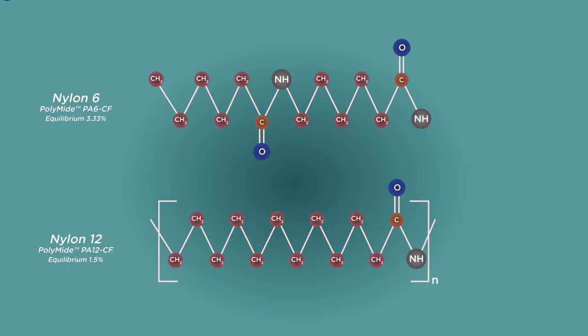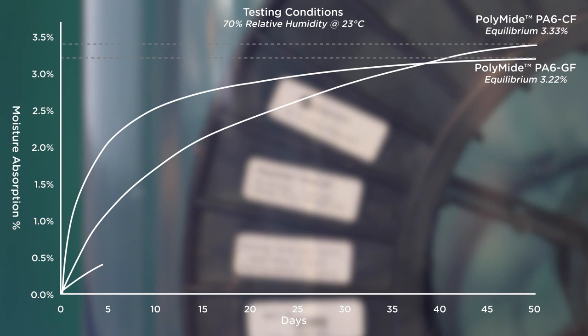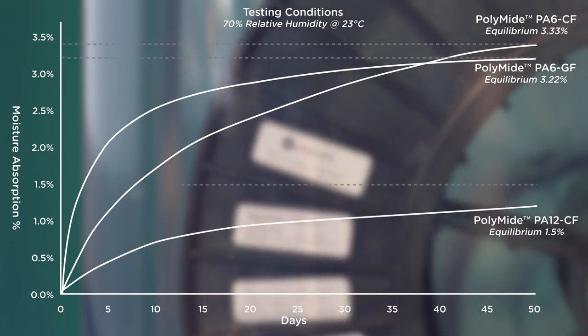For the simple fact that the nylon 12 chain is twice as long as the nylon 6 chain, it means there are half as many amide groups inside the mass of nylon, leaving fewer places for water to be absorbed into the nylon. In other words, a higher proportion of nylon 12 filament is hydrophobic and therefore unaffected by moisture, whereas the nylon 6 has more amide groups and can make more bonds with more water molecules.